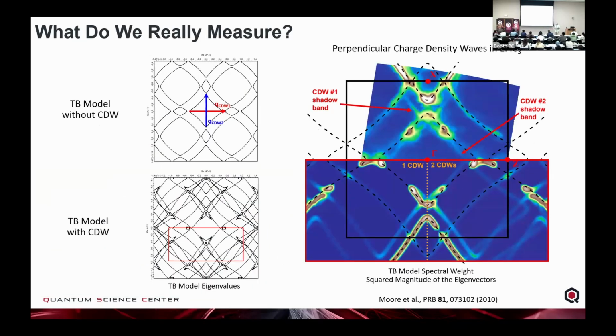But now one important thing to remember is that ARPES is related to the band structure, but we don't directly measure the band structure. So here's the charge density wave material that I showed you before. This is the normal state. When you go down into the charge density wave state, you have these multiple charge density waves that reconstruct what this electronic structure should look like. And this is evidence of the Fermi surface, where we take our multi-dimensional data set and just look at one energy in Kx and Ky at zero energy, and this is the Fermi surface.